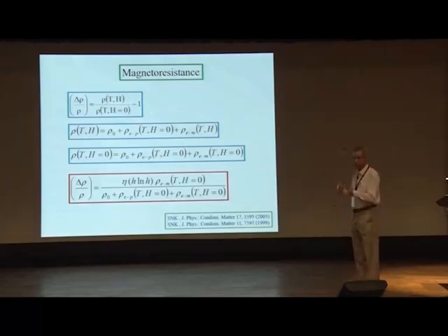So you have to recast your earlier expression into what you see in experiments. That is what this final expression is. And this is nothing but the zero field resistivity, which we had already done earlier. Now we do the same thing for the in-field case, and from that we calculate the magnetoresistance and see how this expression forms.